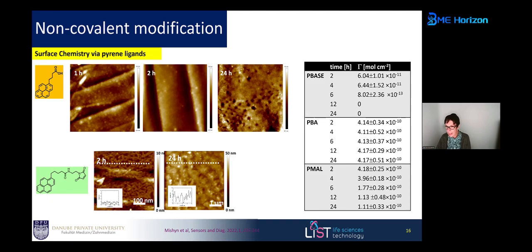That's the reason we believe, and in all our work from this time onwards, we use maleimide modified pyrene ligands on the surface. Because what we see here is we can easily integrate the bioreceptors in a concentration-dependent and time-dependent manner on the interface without losing the sensing possibilities and having a very nice and thin film. So that's enough now on the chemistry for itself. I want to go now to some examples of what you can do with these interfaces.